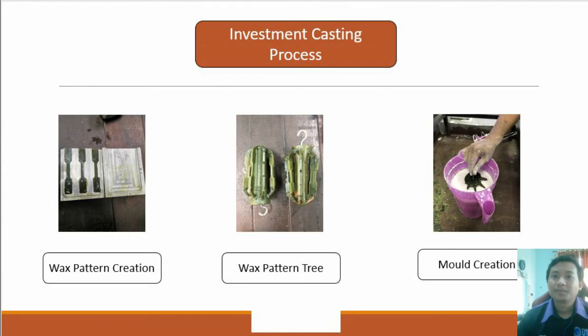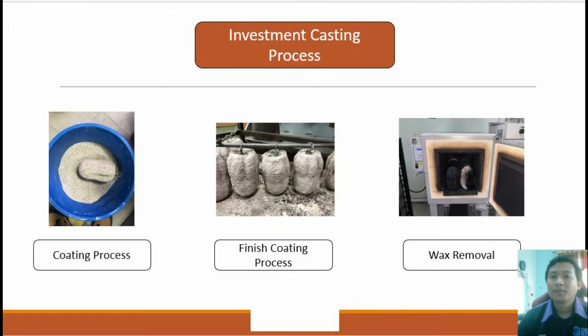The mold creation. The wax pattern is dipped into a slurry of fine ceramic known as zircon powder, 200 mesh, mixed with colloidal silica. The mixing ratio for this slurry is 3:1. The viscosity of the slurry is measured with a Zahn cup. The ideal viscosity time for the slurry is between 40 and 60 seconds. The process is repeated 8 to 15 layers until the shell is between 8 and 10 millimeters thick, as thick as possible to withstand the molten metal it meets.